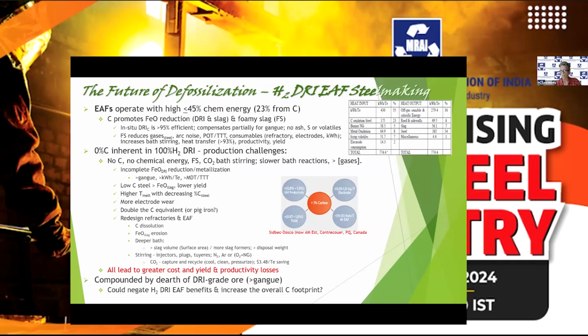Without the chemical energy and the chemical carbon reaction capabilities, we're going to have incomplete reduction of the FeO, less metallization, and more gangue in the furnaces. If we have lower carbon steel, we're going to have more FeO slag and lower yield. We're going to have higher temperature of melting and more electrode wear. And when we're injecting carbon equivalents, we're going to have twice as much to inject because of the efficiency being lower. And we're going to need to redesign the refractories in the arc furnace because the carbon in the bricks that are current are going to be basically dissolved.